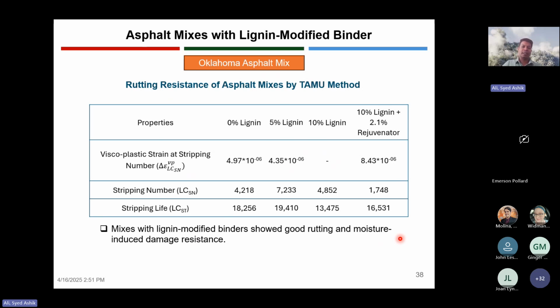If we analyze the results using the TAMU method, there are 3 parameters that we wanted to see. One is the viscoplastic strain at the stripping number. A lower value is good. We have seen that with 0% lignin, it was 4.97 times 10 to the power minus 6, whereas at 5% lignin, it goes down a little bit. For the 10% lignin, we could not calculate it. The software that we are using was giving some error, so we could not calculate that. And then with 10% lignin with 2.1% rejuvenator, the viscoplastic strain number increased. So it shows that the rutting may go higher with the use of rejuvenator.